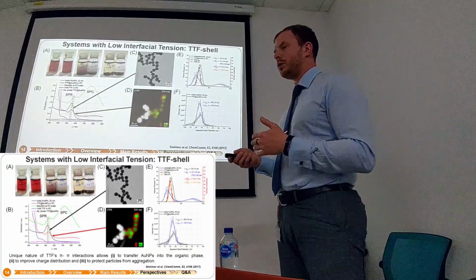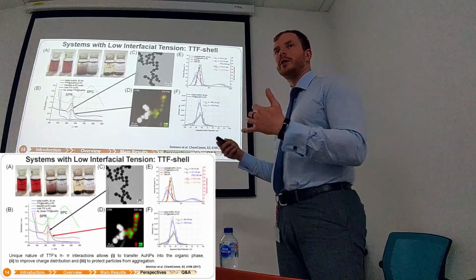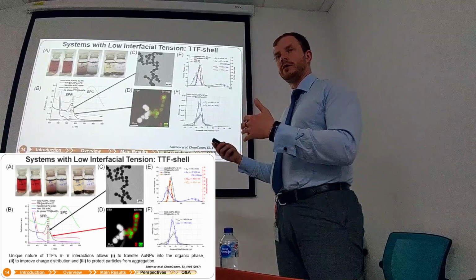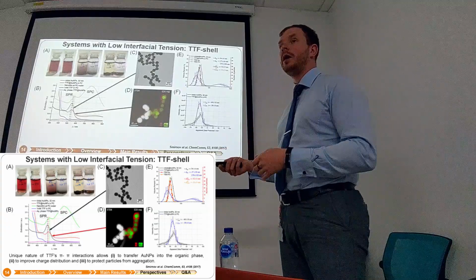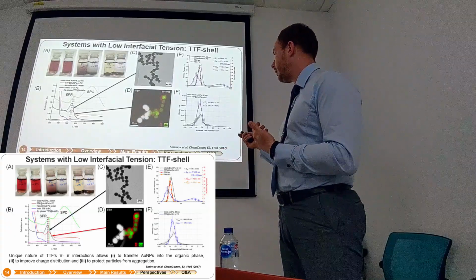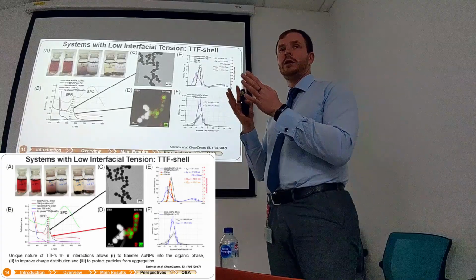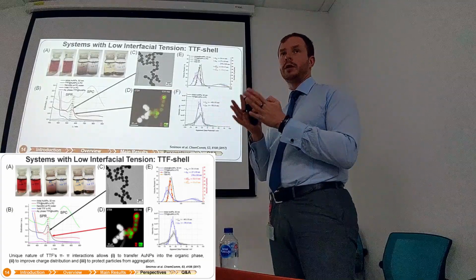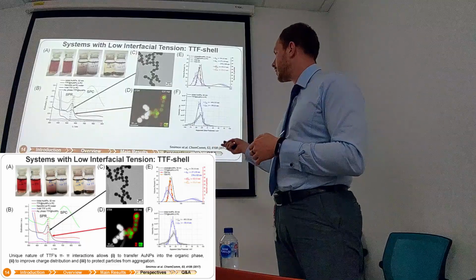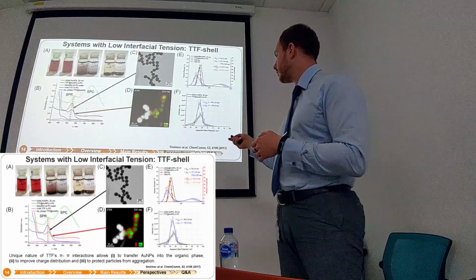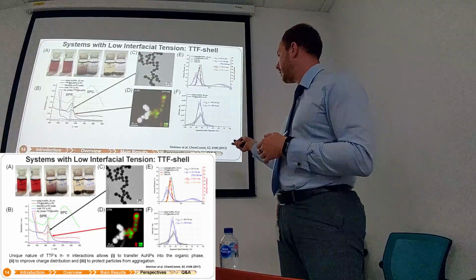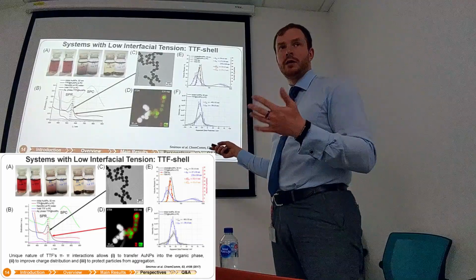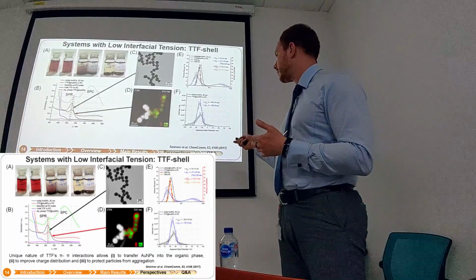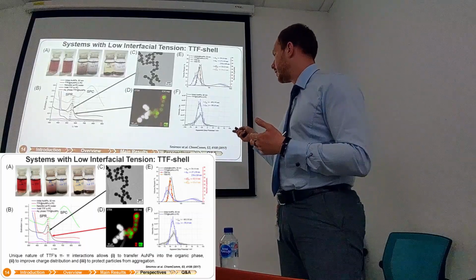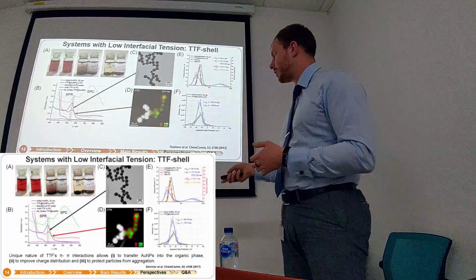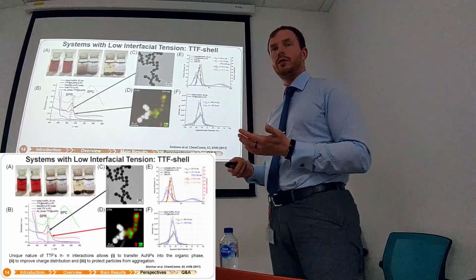And also what we showed and why this suspension is so stable and why we can concentrate this gold ink up to 10-15%, because we sharpen the distribution of nanoparticles by charge. So this is like zeta potential. In water it was like this, very broad. Some particles were at zero, so meaning that they're kind of ready to aggregate. And in propylene carbonate, it's really a sharp peak, positioned roughly at 35-40 millivolts, meaning that it's a